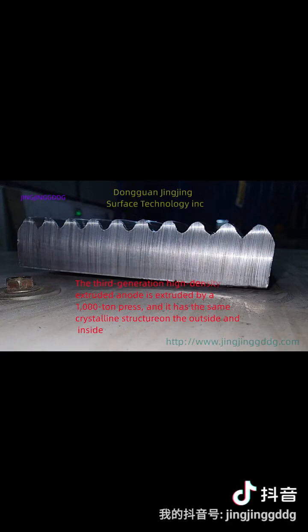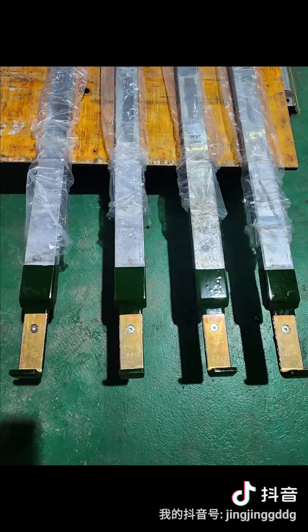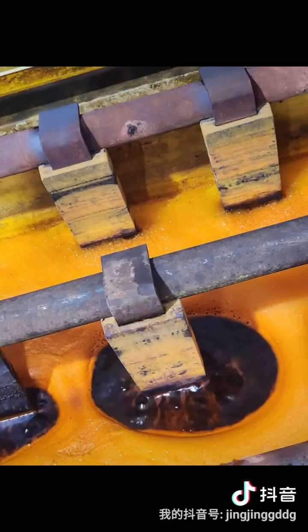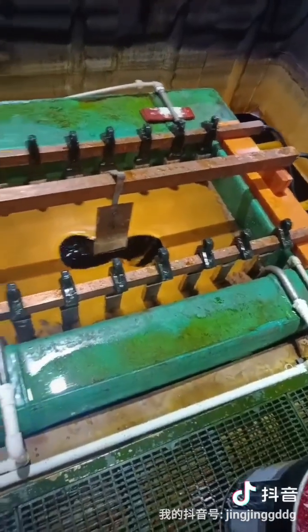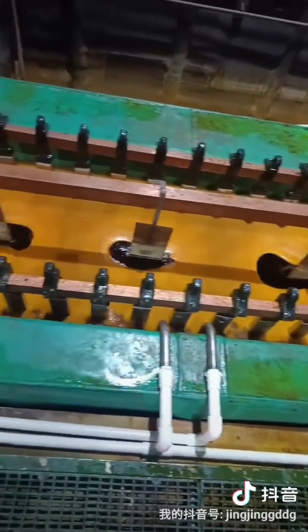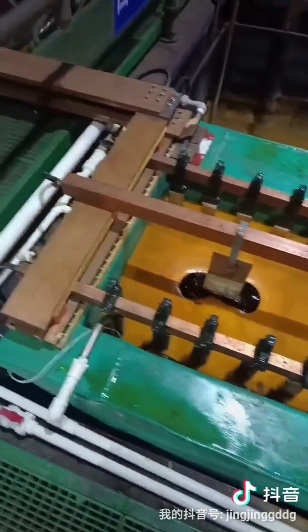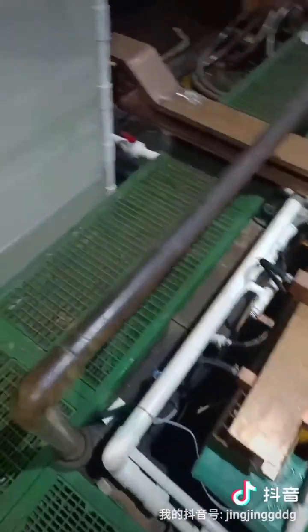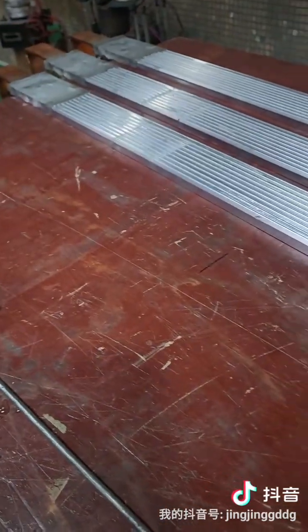We have also optimized the shape of the hook, maximizing the contact area between the hook and the conductive rod, conductive strip, reducing resistance, and thus improving conductivity efficiency. This greatly improves the anode's lifespan and conductivity, with a service life of 3 years or even more than 5 years for products with high tin content. The conductivity has generally increased by about 30%.